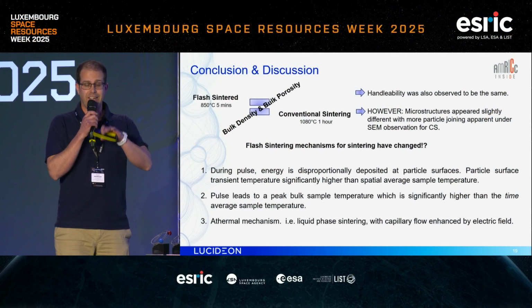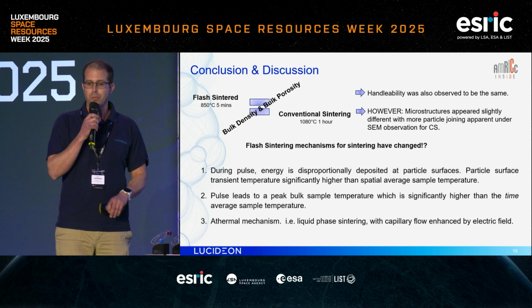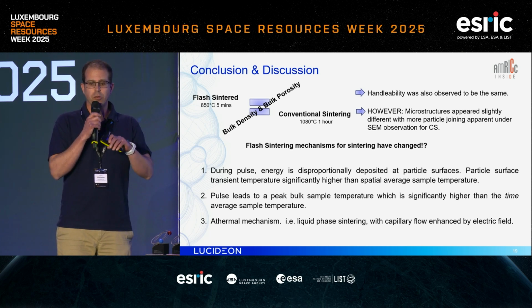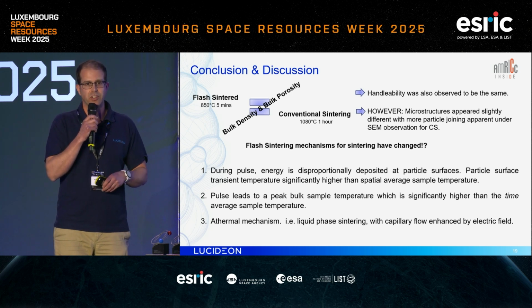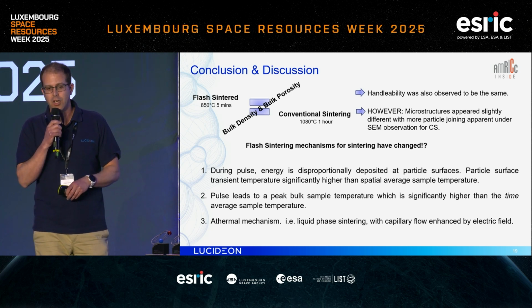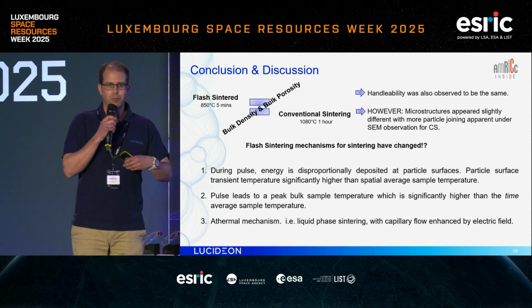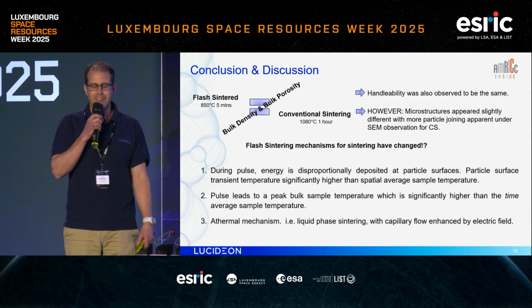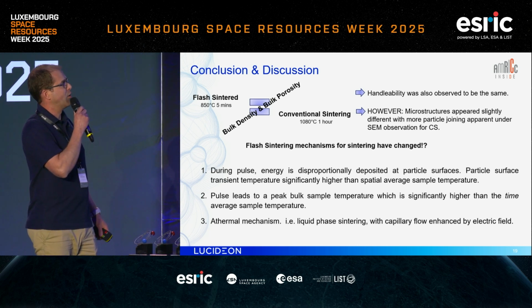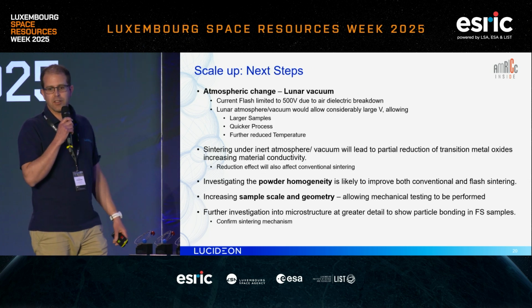Potentially, though, during the pulse, the heat is disproportionately deposited at particle surfaces, or maybe the pulse leads to a peak bulk sample temperature which is significantly higher than the time-average temperature that you would measure. So, some proposals here, something to think about, and something to investigate next time. But what would be next?